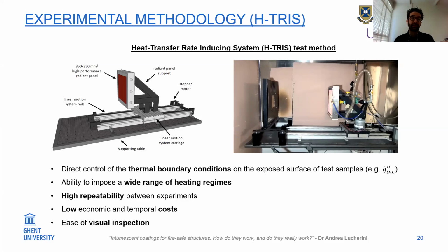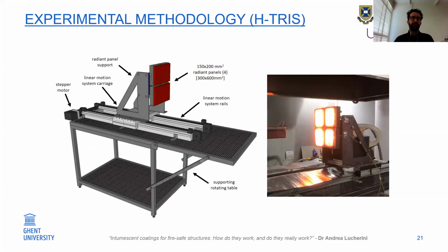It has high repeatability between experiments and low economic and temporal costs, for example compared to a standard fire resistance furnace. Also, which is very important for the case of intumescent coatings, it allows visual inspection of the sample during testing, something that is very challenging during standard furnace testing. So this is, for example, how the system that I developed at the University of Queensland looks like.